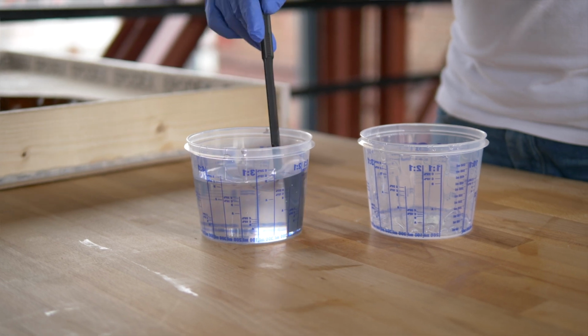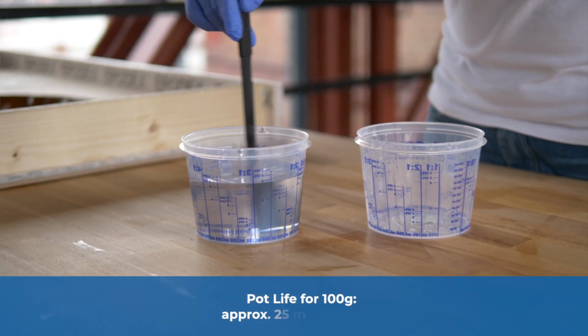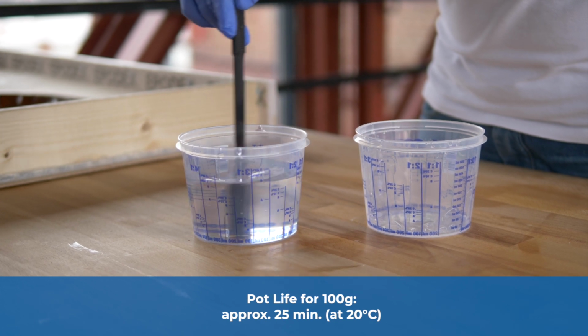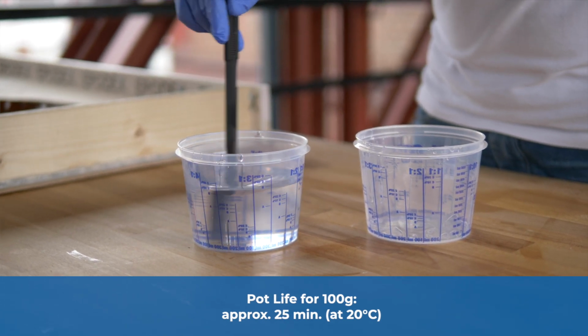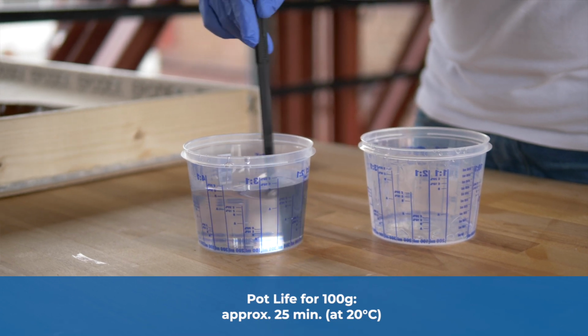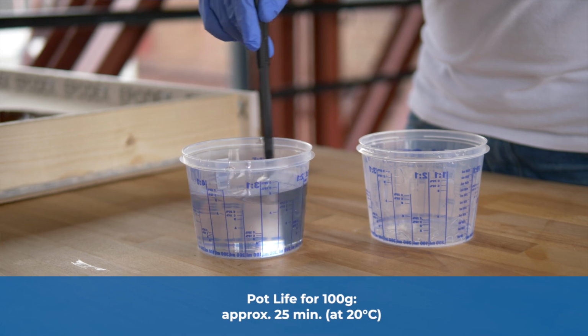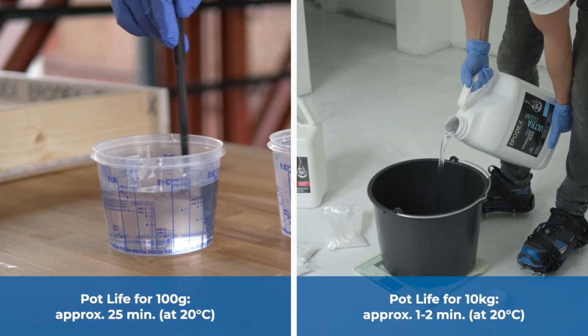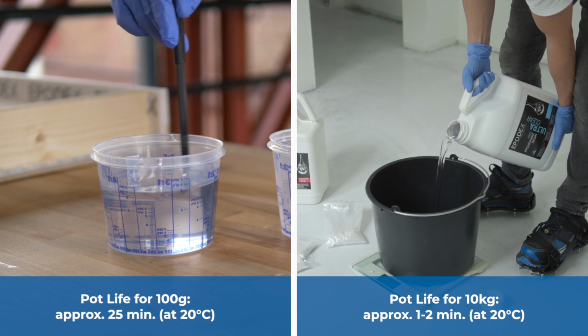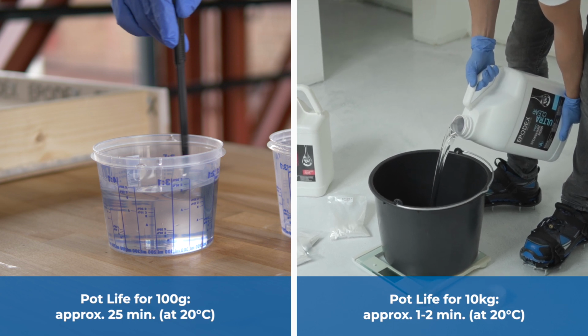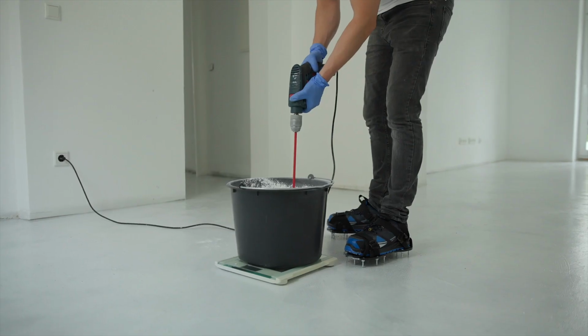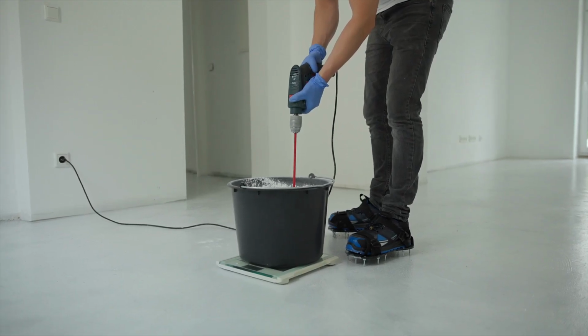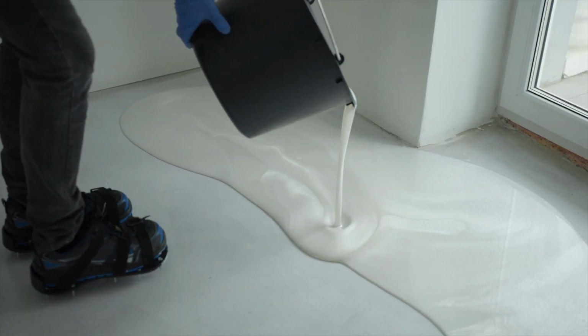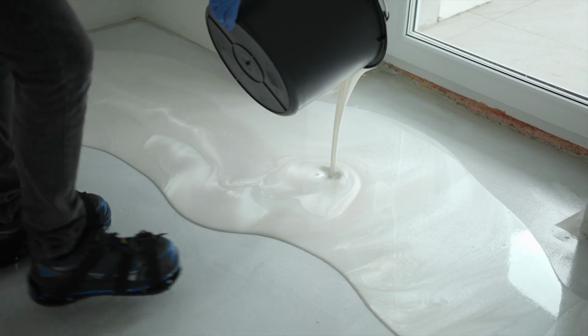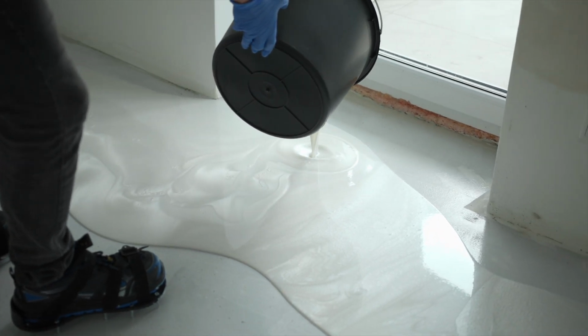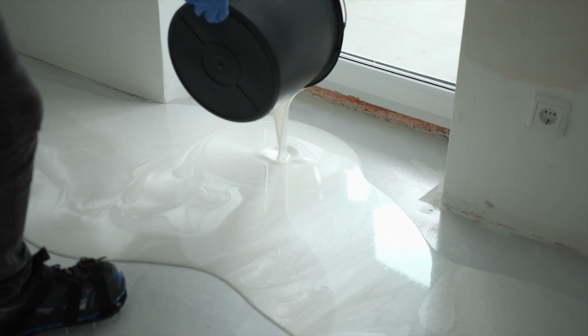The three factors already start to influence each other in the mixing jug. After mixing 100 grams of resin and hardener, the Eco system starts to gelify after approximately 25 minutes at 20 degrees Celsius, meaning it has the consistency of a gel. This time frame is called the pot life. If you mix 10 kilograms of the Eco system or increase the temperature, the system will react within a few minutes, which could lead to curing inside the mixing jug. That's why we recommend, when using a reactive epoxy resin system, to pour the mixture onto the surface to be coated immediately after mixing. This prevents a premature reaction and shortened processing and curing time. You should always consider all three factors in order to control the reaction.